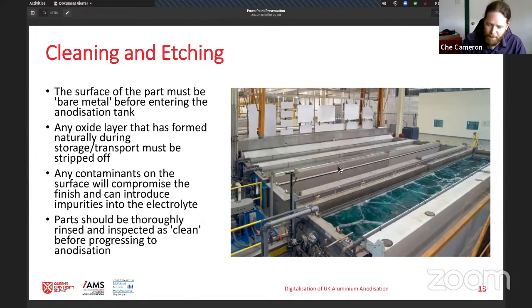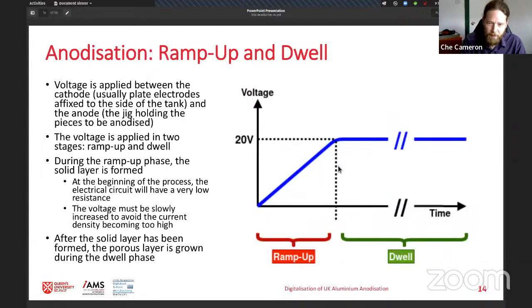So we have now bare metal parts, very, very clean, in their jigs, and they're put into an anodization tank, which is this electrical circuit. At the start of this process, we apply a voltage between the cathode and the anode, and the current is transferred via the electrolyte. That voltage is applied in 2 stages: we have a ramp up stage and then a dwelling stage. During the ramp up, that's when we get that solid barrier layer of oxide formed.